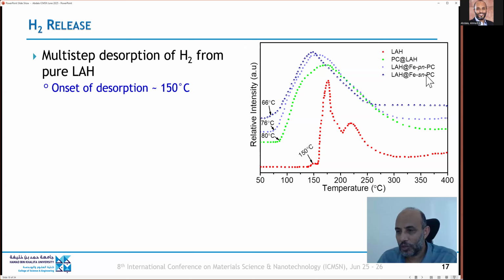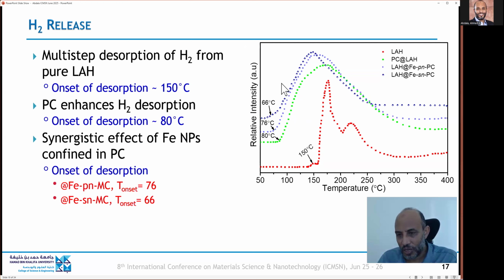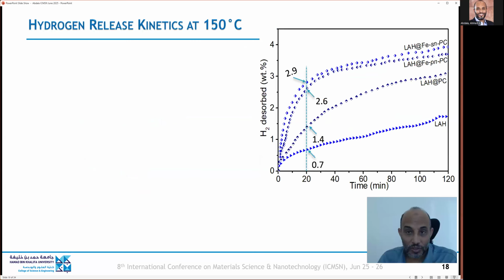And the best performance we get is when we use the catalyst prepared by the sonication-assisted technique. We reduce the onset temperature to about 66 degrees, and we reduce the maximum hydrogen release temperature to about 150 degrees. So that's actually a significant enhancement using the catalyst with the sonication-assisted technique. If we look at the kinetics, here we're looking at the hydrogen release at 150 degrees at different times. So we can see here for the lithium aluminum hydride,